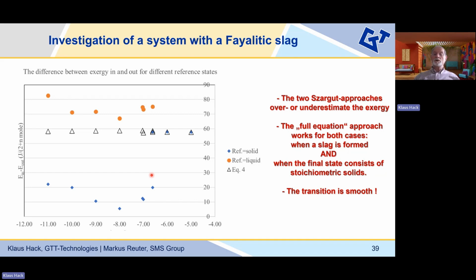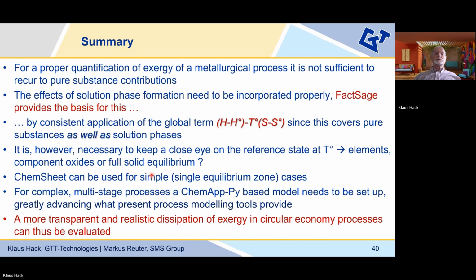It's much better to have only one possibility which is consistent throughout. So as a summary, we can say, for a proper quantification of exergy of metallurgical processes, it is not sufficient to recur to pure substance contribution. That is quite obvious. The effects of solution phase formation need to be incorporated properly, not by way of trying to estimate activities, FactSage, of course, provides the basis for this.